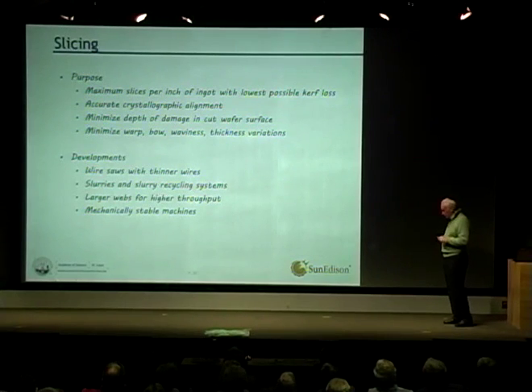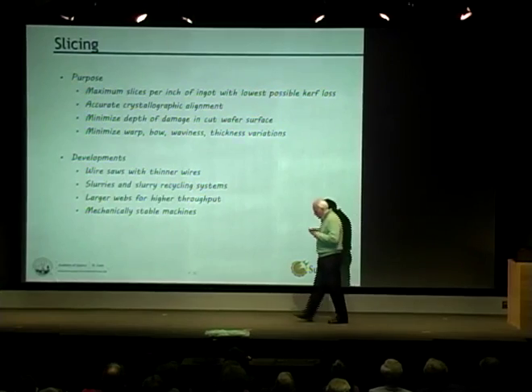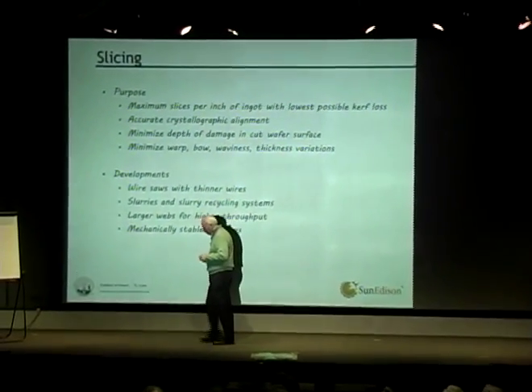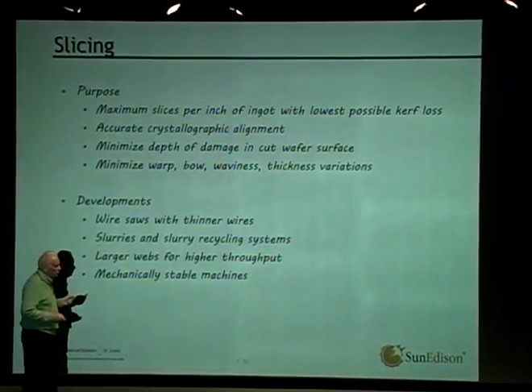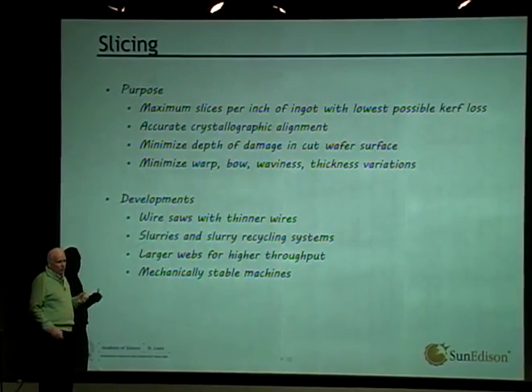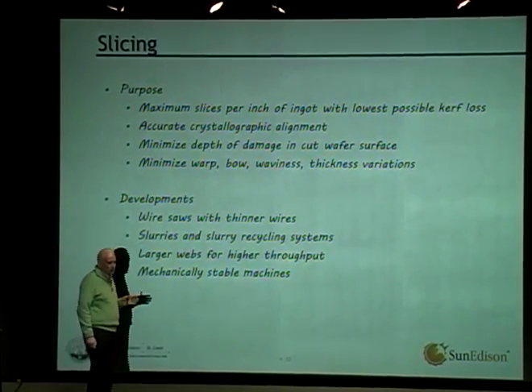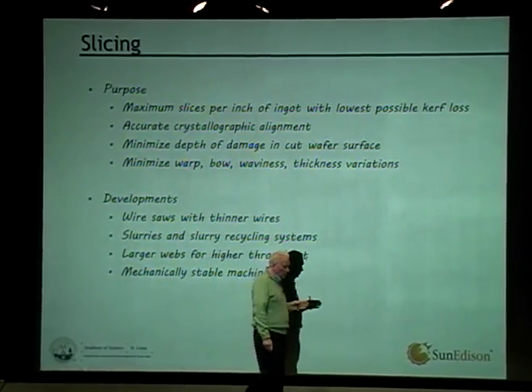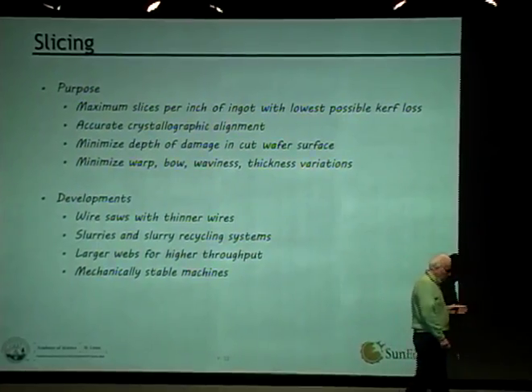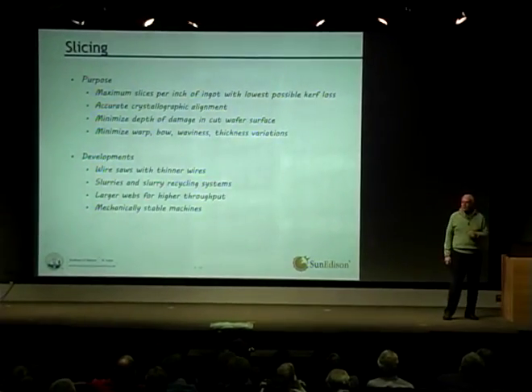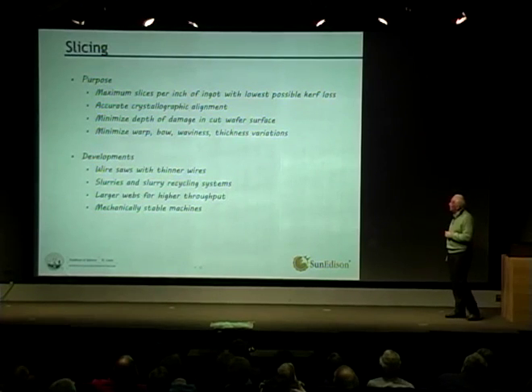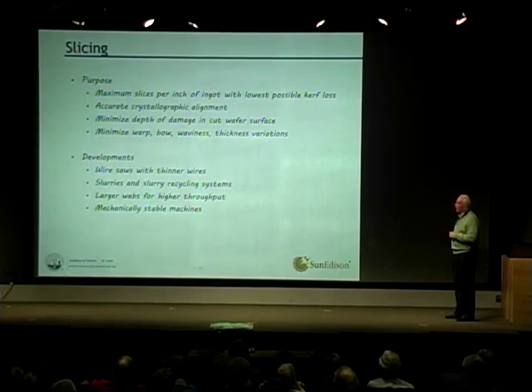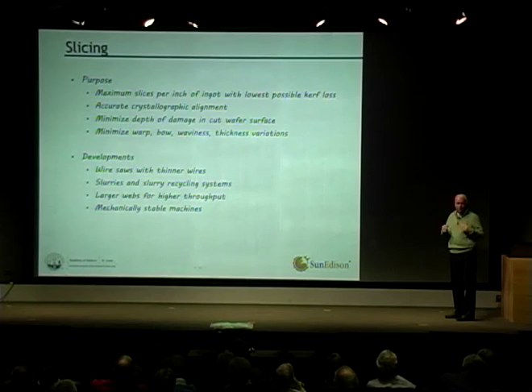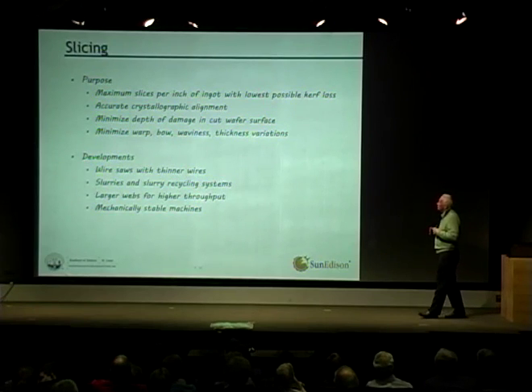Okay. So here's the thing about slicing. I was saying that this part of the operation is glorified machine shop. Well, that's a little bit of a disservice to the guys that work on this stuff, because these saws have very thin wires, about 150 microns, a little bit thicker than a human hair. You've got lots of them going round under tension, and then we put this great lump of silicon. So you have to have very careful tensioning of the wire. The machine has to be very stable, so it's built from very stable machine principles. And then we cut this thing.